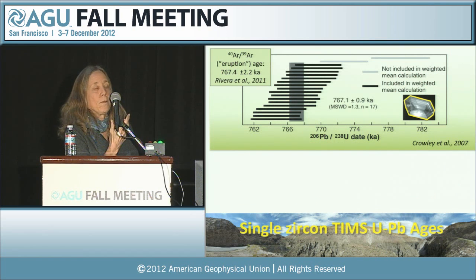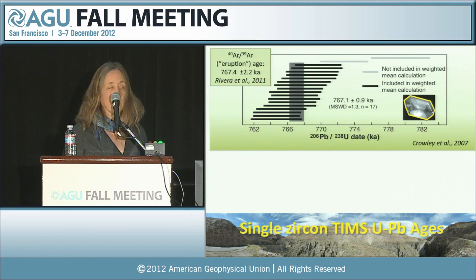Now, in potential support of this are the results of Crowley et al., who dated single crystals of zircon from the Bishop Tuff, and the results of those ages are shown here with two outliers that sit up in here. And they obtained an age of 767,000 years, which is an excellent agreement with the apparent eruption age for the Bishop Tuff of 767,000 years. So it appears that these crystals formed very close to the time of eruption.